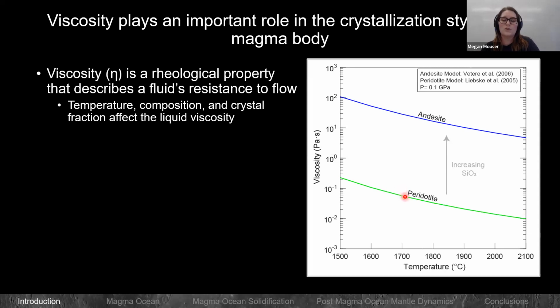And if we look compositionally between the peridotite and the andesite, the main compositional difference is the silica content. Peridotite is very silica undersaturated, and andesite is an intermediate type rock, so it has an increased silica content. You can see that with almost 3 orders of magnitude difference between their viscosities, that clearly makes a difference. So composition plays a big role in this. Crystal fraction, I'll get into a little bit later, but when you start introducing crystals into a liquid, it takes it from behaving as a Newtonian liquid to more of a plastic. So we'll see that effect happening a little later.